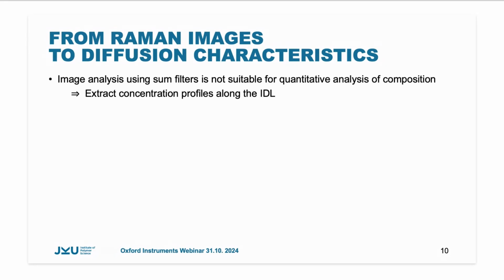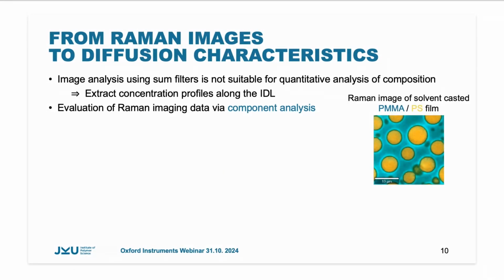Therefore, we have to analyze the images. Image analysis using the sum filters has shown not to be suitable for a quantitative analysis of the composition, meaning to extract concentration profiles along the interdiffusion layer. On the other hand, we could choose component analysis for imaging.